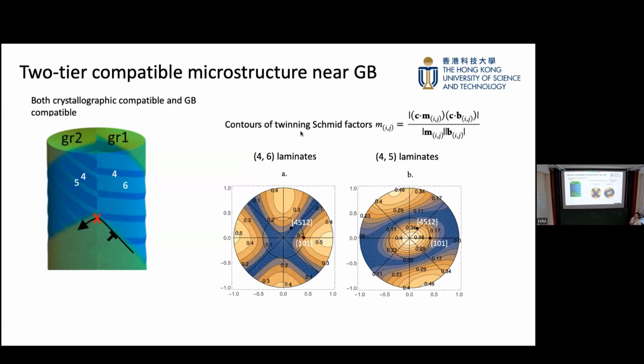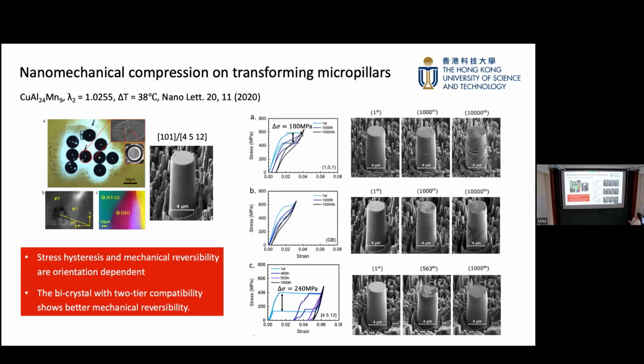So again, this is our conjecture. We think this is probably the way to really improve the material reversibility under stress. And what we do is we find a grain boundary and we make a bicrystal pillar. We hope half of it is one grain and the other half is another grain. And then, okay, the middle row corresponds to the bicrystal, and we find that this material is very interesting. The residual strain, the permanent strain, is the least. That means if we load it up and down, although the total transformability is sacrificed because we didn't really maximize the axial strain, the reversibility has been much enhanced due to this kind of accommodation within each other.